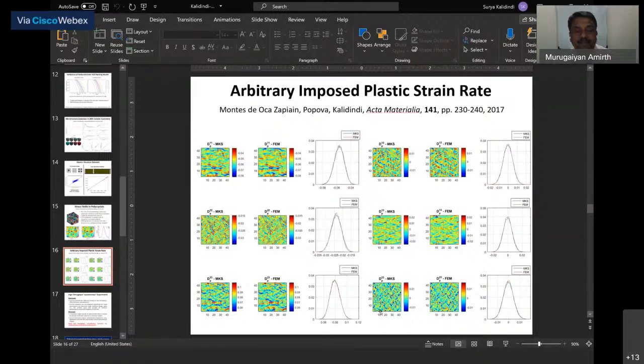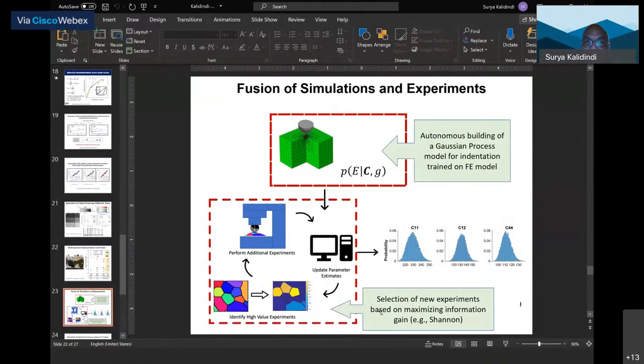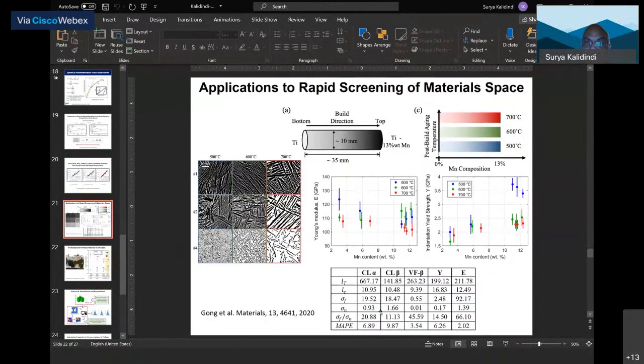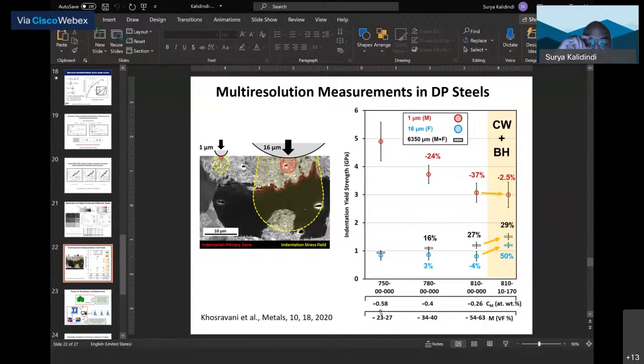Okay, so that also is a very good question. There's a lot of literature on what is called the indentation size effect, ISE, and that is a very different thing. They're not talking about different indenter tip sizes. They're talking about when they do an indentation with increasing depth, they find a different value of hardness. So that's a very different phenomenon. It's not the same thing that I'm talking about.